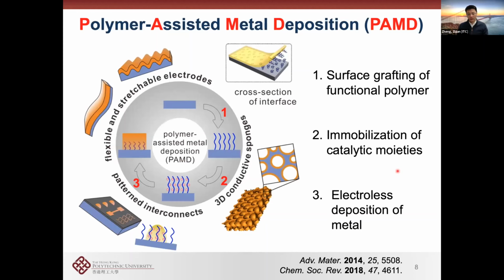To address this question, we developed a chemical approach we call polymer-assisted metal deposition, which grows metal from the bottom up, versus the top-down approach that I showed you just now. Basically, the idea is to modify the substrate, whatever the substrate and structure, with a thin polymer layer. This polymer is designed to immobilize catalytic moieties, which allows you to do electroless deposition, a reduction process of metal in a chemical, liquid environment. So you modify the substrate with a polymer, which allows you to grow metal from the bottom up to form very soft, adhesive, and highly conductive metal electrodes, right?